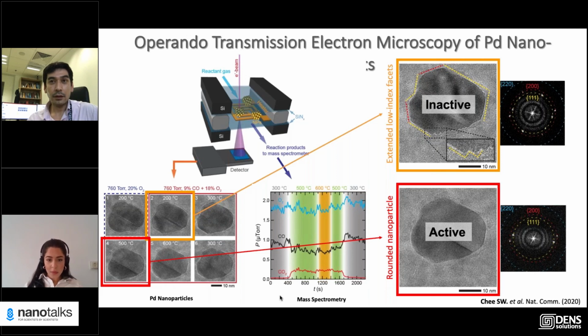But what I would like to shift the focus to is a little bit towards real-life catalysis, because this is what we do in general, and we would like to see more results towards that. Some of the things that you show, for example, the way that carbon monoxide shapes the crystallography on the surface, I'm not so sure whether that would happen if that palladium was sitting on an alumina support, for example, which is what you would have in a normal autocatalyst.